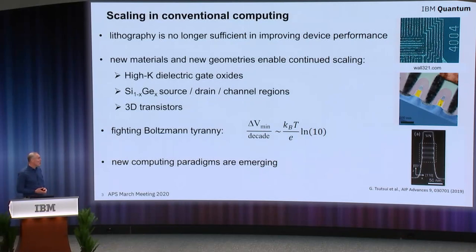The fact that the oxides used to insulate between the gate and channel regions are so thin they're no longer insulating, and cases where we actually have to tune the strain within device channels to improve carrier mobility. In some cases, we've moved from a planar geometry to three dimensions to get better electrostatic control. But even accomplishing all these feats, we're hitting a thermodynamic hard limit — referred to as Boltzmann tyranny — the fundamental voltage that must be supplied so we can distinguish between on and off states. Therefore, we have to look at different paradigms, and I would argue quantum computing is the leading contender.